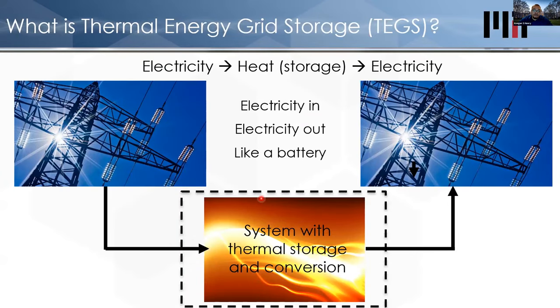We're doing it in a way that will sound totally non-intuitive, and if you've taken a thermodynamics class, it's going to sound stupid. What we're doing is going from electricity to heat back to electricity. And the reason that would sound stupid is because we expend most of our effort going from heat to electricity the first time. And when we do so, we pay a very big thermodynamic penalty. We generally lose more than half the energy. If you then go electricity back to heat, you can do that at almost 100% efficiency. The problem is when you go back from heat to electricity a second time, you're going to pay another big penalty, another 50%. So it sounds kind of dumb to do this, but I'll tell you why.